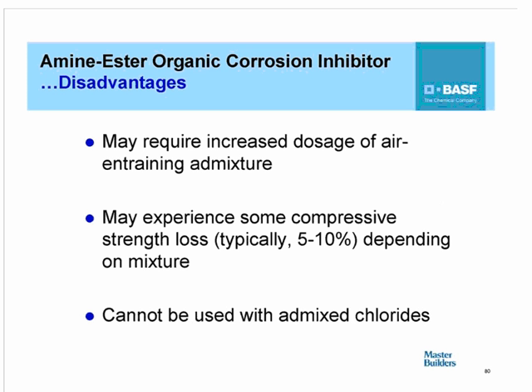The main disadvantages of this particular product is the fact that it does require increased dosages of air entraining admixtures when used in concrete. And also, depending on the composition of the mix, some loss in compressive strength may occur, typically in the range of about 5 to 10%, depending on the mixture. But for the most part, when used in concrete mixes that are proportioned for corrosion resistance, the loss in strength is not anything that affects the specified compressive strength of the concrete. Another disadvantage of this material is the fact that it cannot be used with admixed chlorides in concrete.